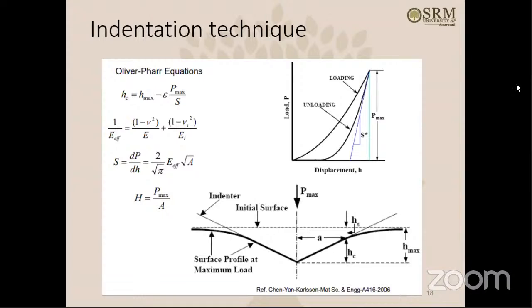This maximum load is P max, and the slope of the unloading curve is called S. You can use this equation with P max and S. If you know S, you can calculate the modulus of the material, and if you know P max, you can calculate the hardness. So there are equations which can give you the modulus and hardness of the material from a simple indentation test. Then, can we use this for our purpose? That's what this project is about.